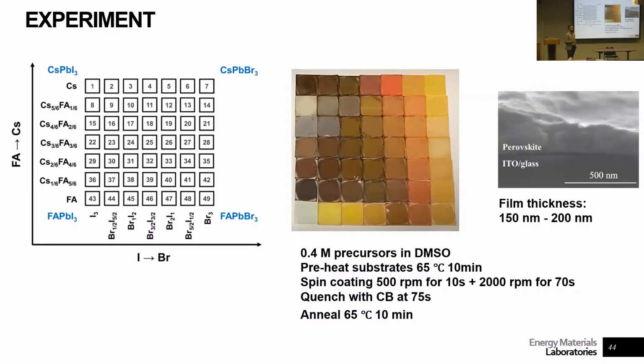Is anything being looked at for lead replacement, any candidate? Tin, but tin oxidizes to tin 4+, sorry, 4+. And that also changes the structure. So tin is super unstable. You remove it from the glove box and it immediately turns white.